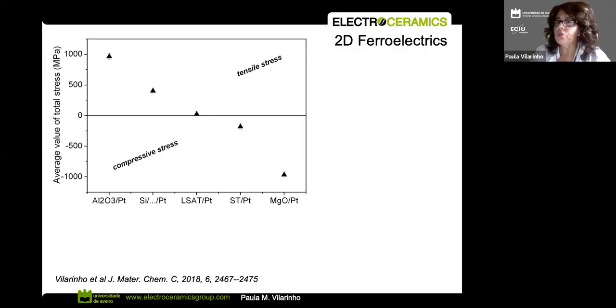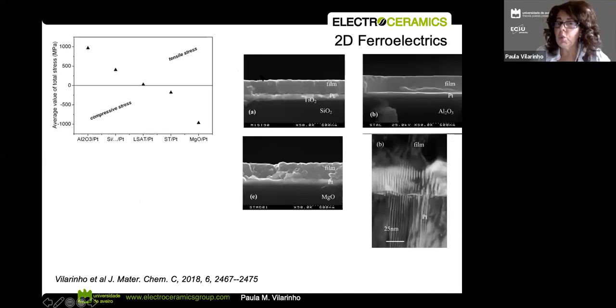What I'm going to show you here is that this material, which I said is really an important material, when I produce it in thin films, this means around 100 to 200 nanometers, I can engineer the stresses of these materials, okay? So how can I do that? I can do that by depositing a film on a substrate that has a different nature from the film. And that's what is represented here.